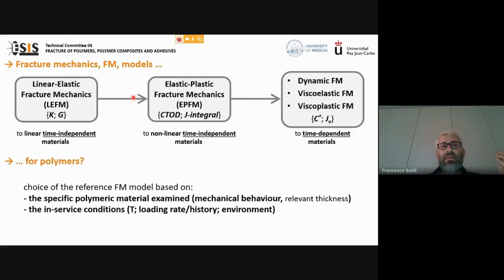Let's arrive to fracture mechanics. Now, concerning fracture mechanics, we know that we can count on several fracture mechanics schemes. Linear elastic fracture mechanics is for time-independent materials in quasi-static conditions, and that is valid if the non-linear deformation region is confined at the crack tip. Within the linear elastic fracture mechanics, we have the toughness parameters, the fracture parameters, which are the K, the stress intensity factor, and the energy release rate. Then we have elastic plastic fracture mechanics that was developed for nonlinear time-independent materials, and the fracture parameters are the crack tip opening displacement and Rice's J integral.